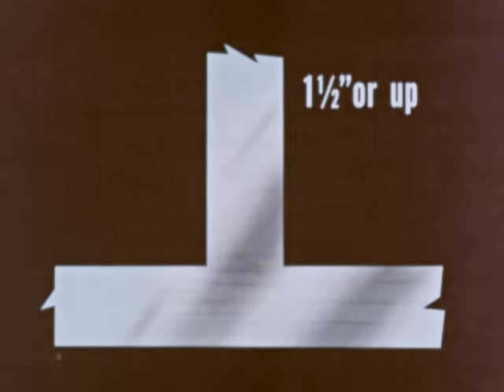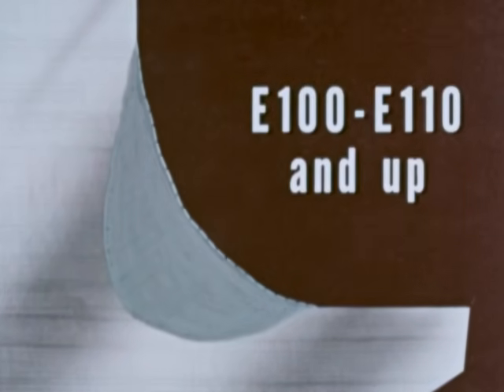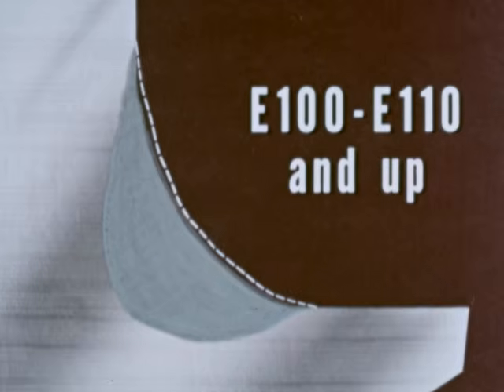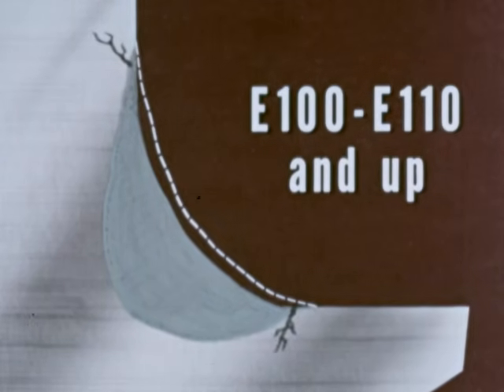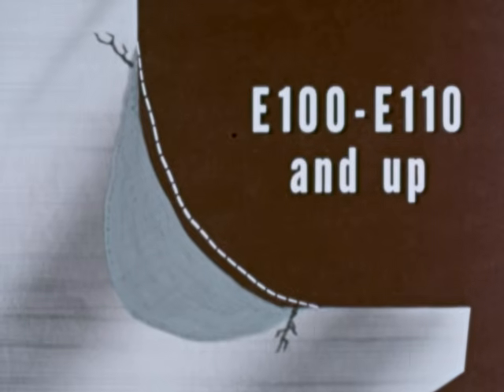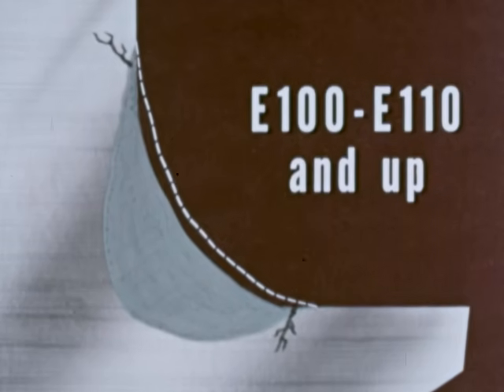Because USS T1 steel is so strong, additional care is necessary. When welding thick pieces, and if the finished weld has to be stress relieved, high-strength rods such as E100 or E110 were specified. As the weld metal cooled and contracted, it was strong enough to actually pull cracks at the toes and seriously weaken the weld. This could have been easily avoided.